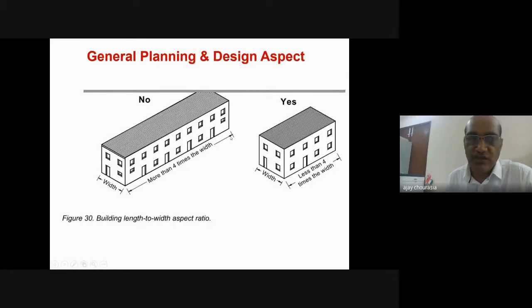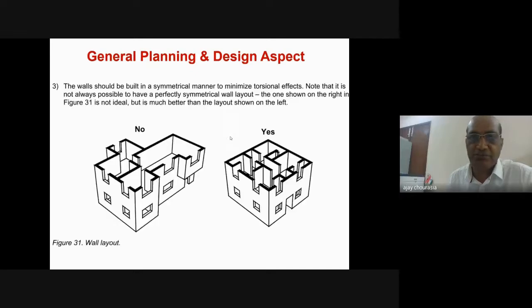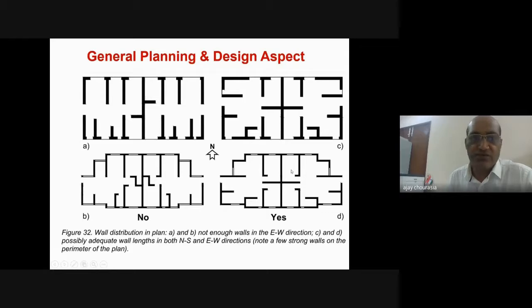Then the aspect ratio is also one of the important parameters. Length to width ratio should be less than 4. If at all it needs to be constructed, you have to provide an adequate separation gap. Then wall layout is also very important. It should be symmetrical in both directions and uniformly placed. On the left side, there is a high amount of wall density in one direction, whereas it is very low in the other, which is not correct. The right one should be encouraged. The general wall distribution should be uniform in all the plan area, not lying in one particular direction.